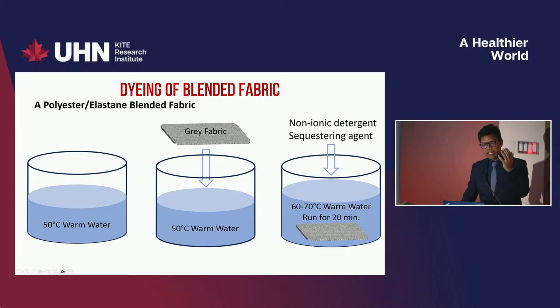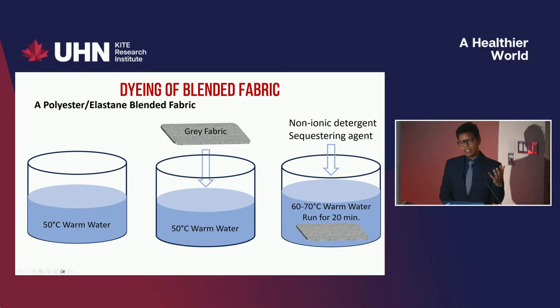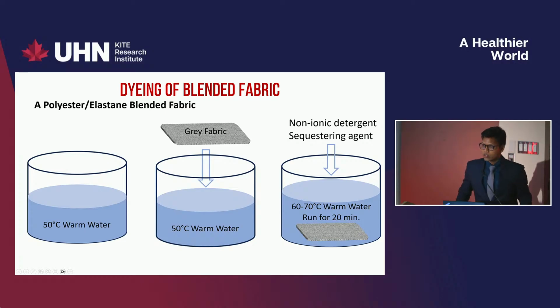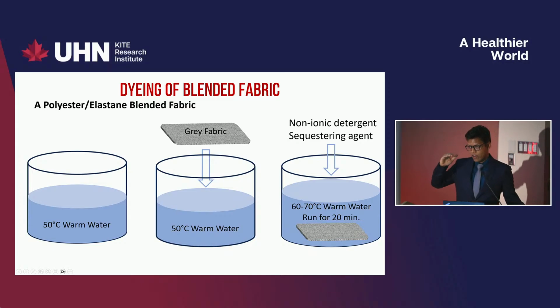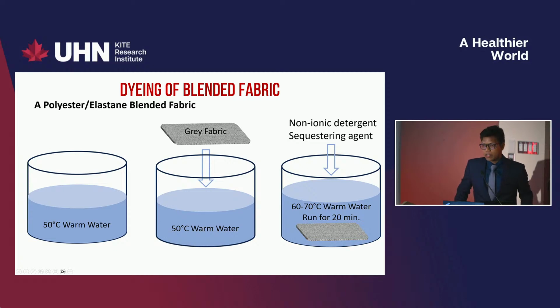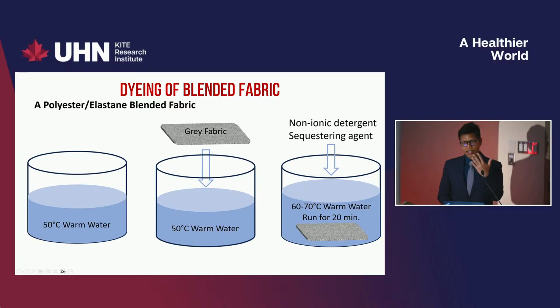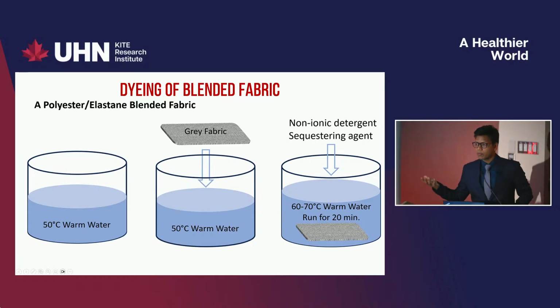However, as the fabric is coming from another department, after weaving or after knitting, if you had the chance to see how weaving and knitting work, the machine has a lot of grease, and this grease usually comes onto your fabric as well. Apart from the machine grease, from other manufacturing steps, from the beginning, the fiber comes with minerals if we think about natural fiber. Also, it comes with other contamination from the machine and other steps. So we use a sequestering agent to demineralize the water so that there is no calcium, magnesium, or any mineral in the water. The sequestering agent takes the minerals so that they do not interfere with the dyeing process.